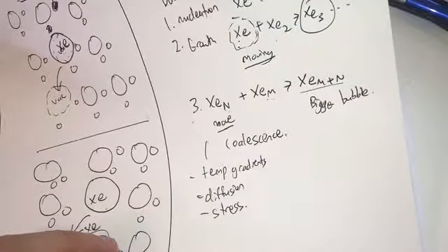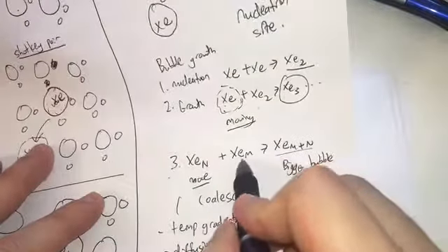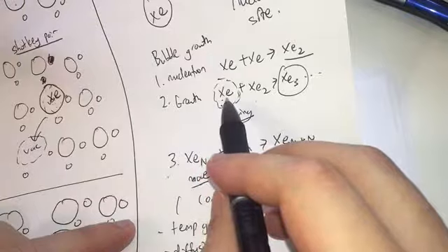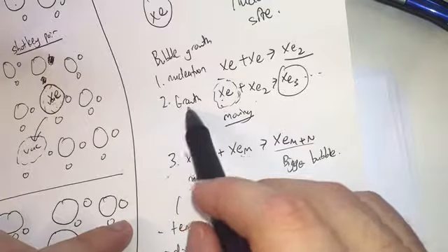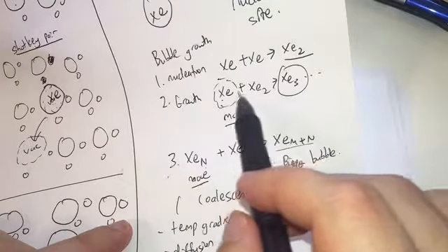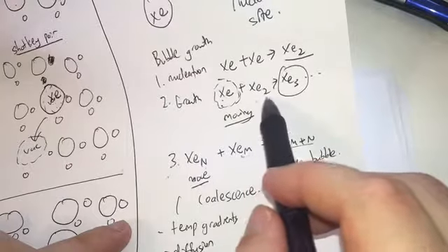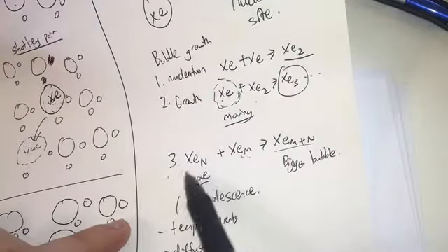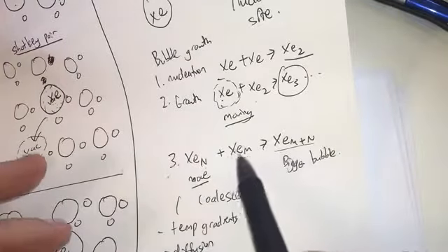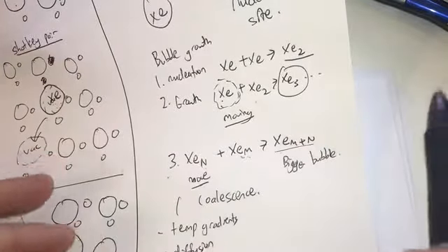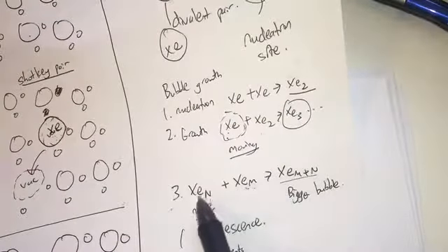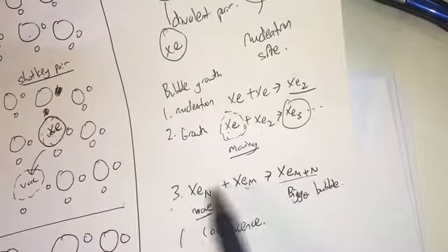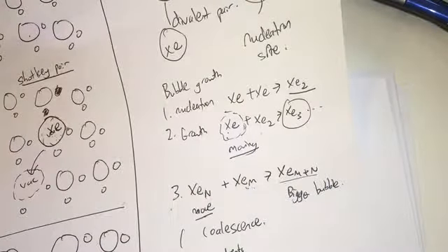But in essence, coalescence will differ from growth. In growth, individual xenon atoms are moving, so the bubble grows atom by atom. But after a certain size, when these bubbles are big enough, the dominant mechanism for bubble growth is no longer nucleation and growth. What happens is that these things tend to join up to become bigger bubbles. This is coalescence. So bubble size tends to increase dramatically.